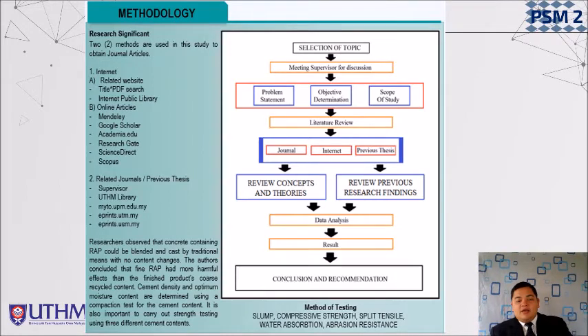Okay, from overall, the researchers observed that concrete containing RAP could be blended and cast by traditional means with no content change. The author concluded that fine RAP had more harmful effect than the coarse RAP on recycled content. Cement density and optimum moisture content are determined using compaction test for the cement content. That is the summary from all the journals that I came across for the method. Methods for testing used in this study are slump test, compressive strength test, split tensile test, water absorption, and abrasion resistance. These are the common methods of testing used from many researches that have been read.